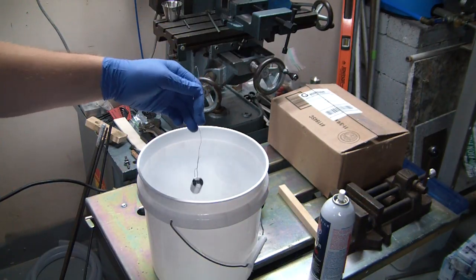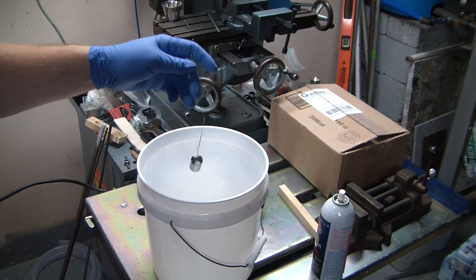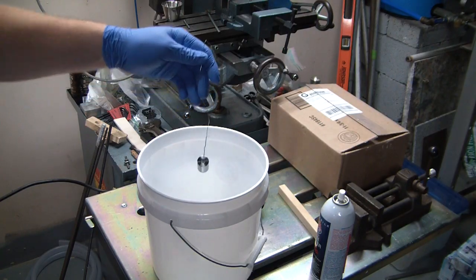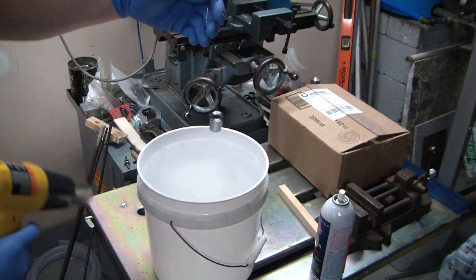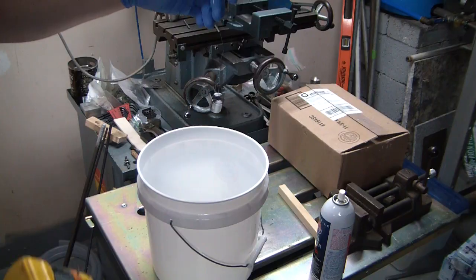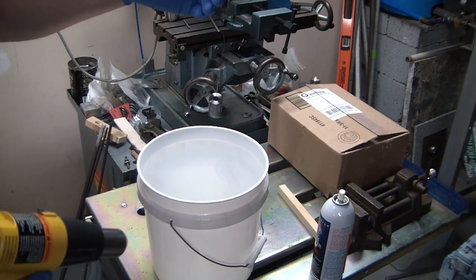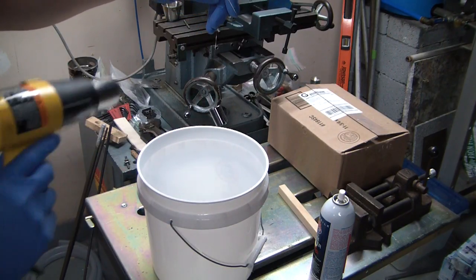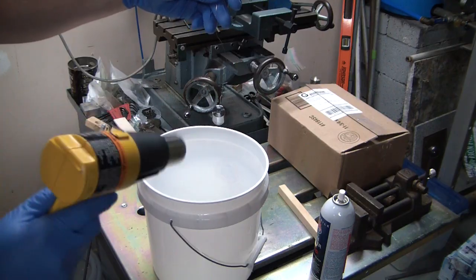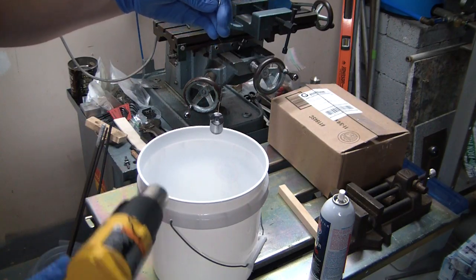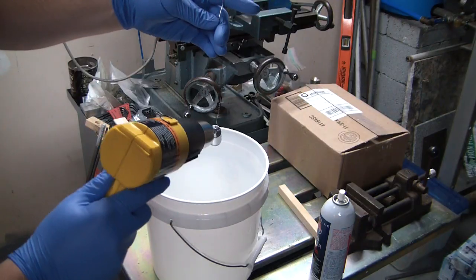You got to be nuts, like OCD level clean here. Any residue on this part and it will not parkerize properly. And of course after you clean it, you cannot touch it with your dirty human fingers. Otherwise your oils will transfer to it.